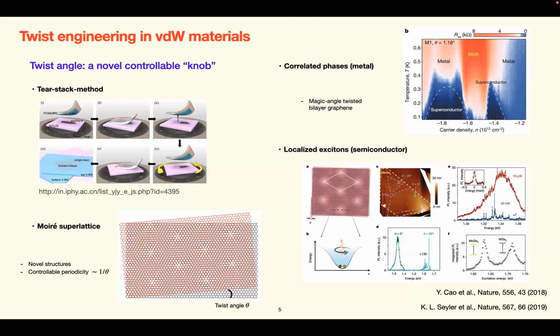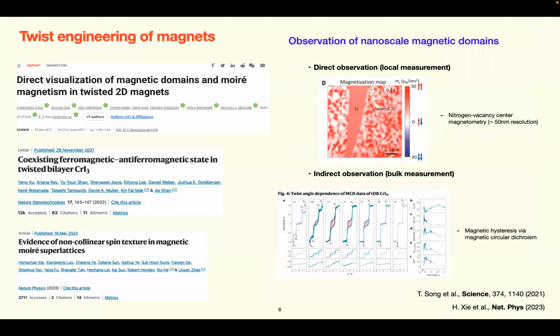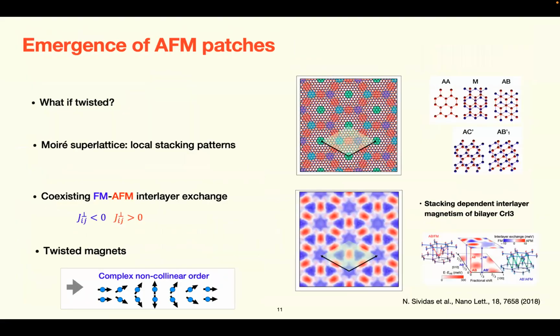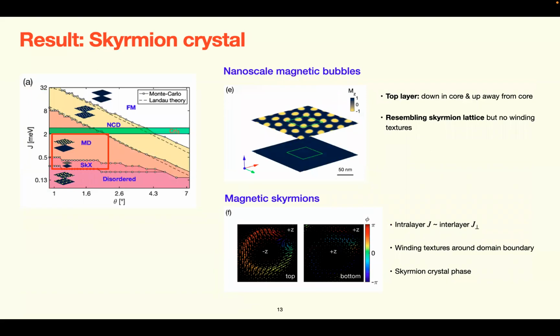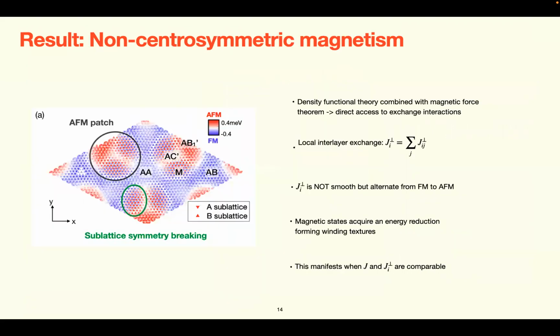But what are typical values? Which are the most interesting? He's asking about the value of the twist angle. I see. So here I used, this corresponds to 1.6 degrees. So the periodicity of your moiré crystal is about hundreds of lattice parameters. Yeah. That's right.